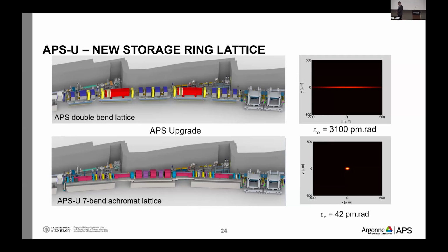And so the promised goal was to reduce the electron emittance in the horizontal direction from 3 nanometers down to 42 picometers. And this, of course, in turn is the reason why you get a much brighter beam at the end. So this project has been in the making for more than 13 or 14 years at this point. So it's a big deal.